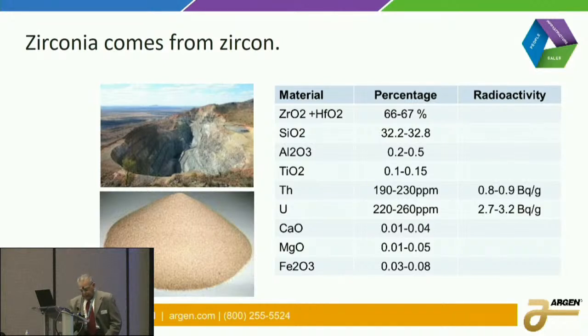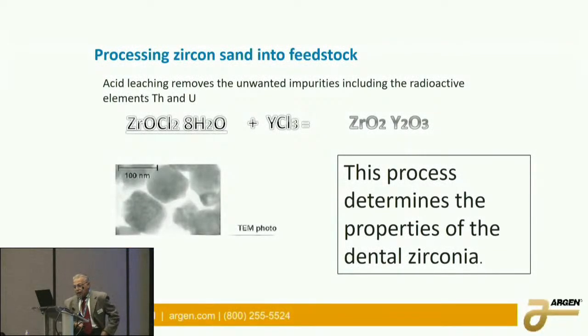And the way to get rid of that is to dump it in an acid. And in this case, the acid is extremely strong. It's hydrochloric acid. And the idea is to drop out everything except the zirconia out of the acid. And this is called a feedstock. Now, this process is done mostly in China because it's so environmentally damaging.